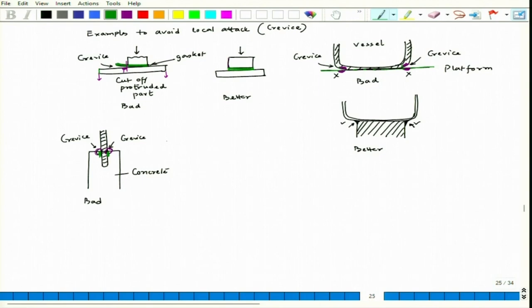And this is interesting, because it is a matter of concentration cell. Because the outside part we have a lot of oxygen, the inner part we have less oxygen. So, it can actually lead to a local concentration cell, and the inside part can have higher degree of corrosion, that means that part is anode. That can be stopped if we have a cement which has very high degree of water imperviousness. Okay. So, that means water cannot ingress through that particular concrete mixture, but still the crevice point can lead to attack in the steel component of the particular rod.